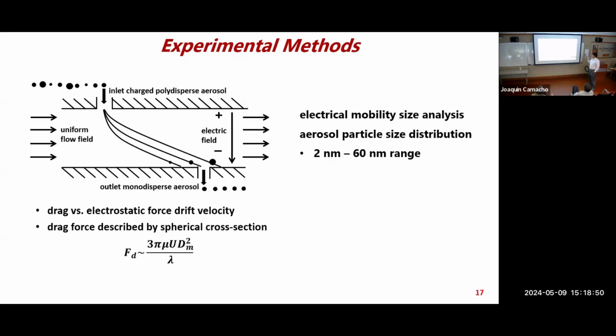The soot in this flame is an aerosol where particles are following the bulk gas flow. Another measurement I'm using is to sample the flow of the aerosol. The particles are still flowing in the gas. If you expose it to an electric field, you can classify or separate a mixture of different size aerosol particles into one single size, depending on the electric field, taking in some assumptions on the balance between the drag force in the flow and the electric force. You can separate these different sizes out, and that's what I'll use, specifically in this 2 to 60 nanometer range, very small, the finest of the fine nanoparticles. This is pretty much molecular scale, but this analyzer is able to separate, measure and count them to get a distribution.